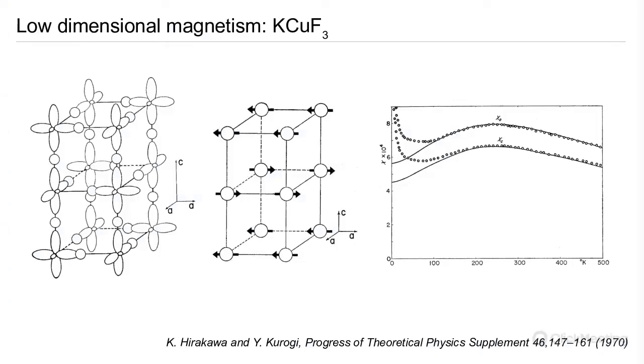Okay, going to another example from the inorganics that I want to talk about: despite having what is really a well-connected, dense, three-dimensional framework, we can find low-dimensional magnetism. And this is a particularly interesting case in point, potassium copper fluorine 3, KCuF3. And we know we have low-dimensional magnetism because it's characterized by this very broad hump in the magnetic susceptibility, where essentially the central position of this hump is characteristic of the dominant one-dimensional exchange interaction in the material.